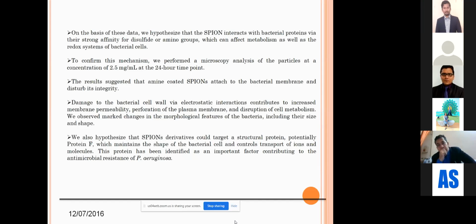On the basis of these data, we could come to the conclusion that it is the SPIONs with the amine group that are able to interact with the bacterial protein via strong affinity for disulfide or amino groups, and can affect the metabolism as well as the redox system of the bacterial cell. To confirm this mechanism, we performed the microscopic analysis, which I showed in the slide, and could see how the surface is getting affected. Within 24 hours of our study, we could see the concentration by which the cell was getting disrupted. So amine coated SPIONs attach to the bacterial membrane and disrupt its integrity.